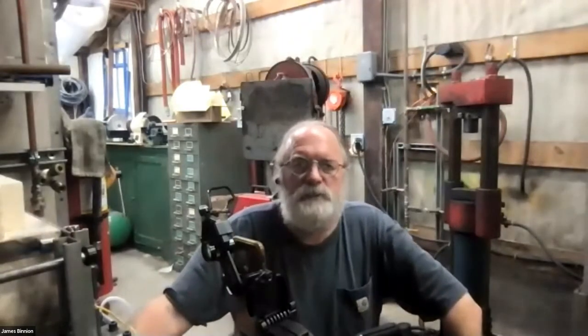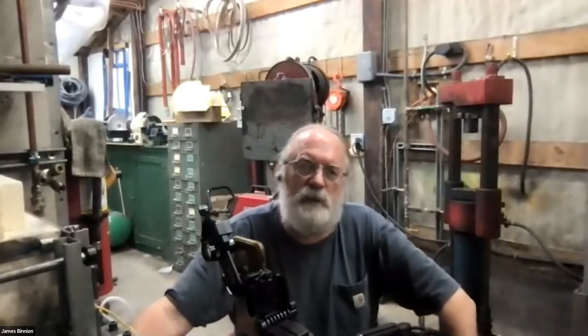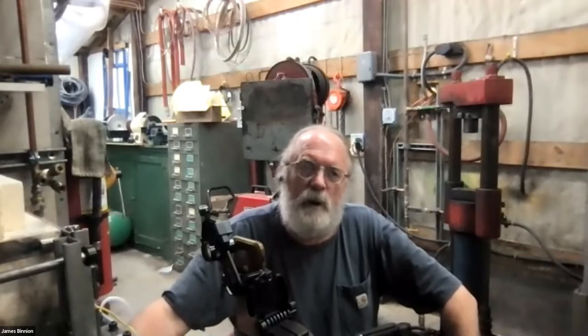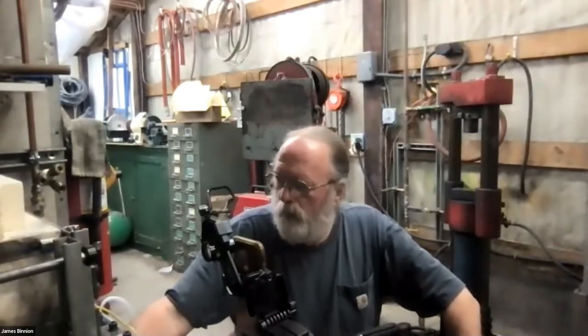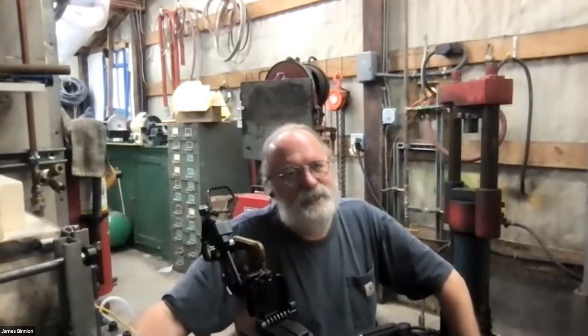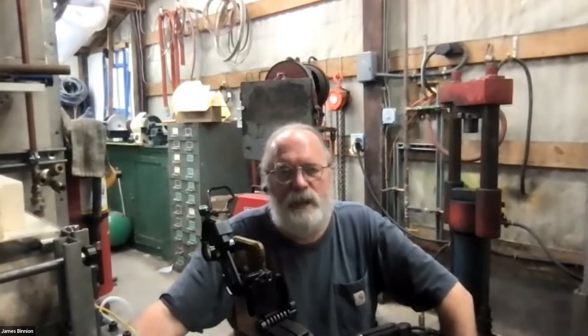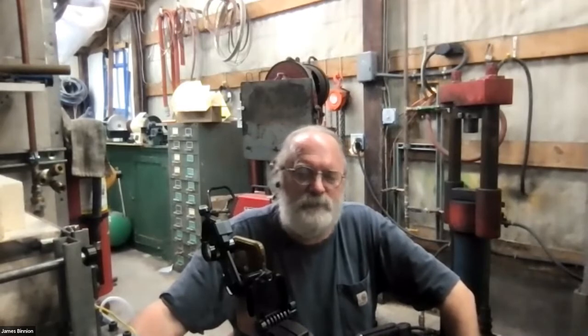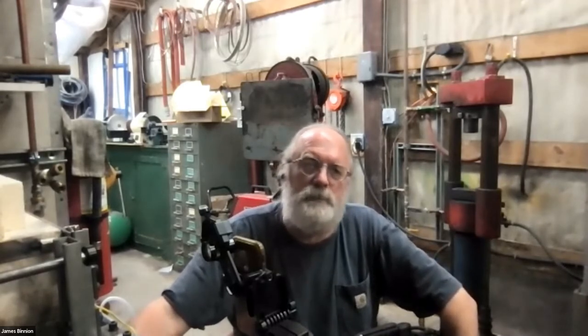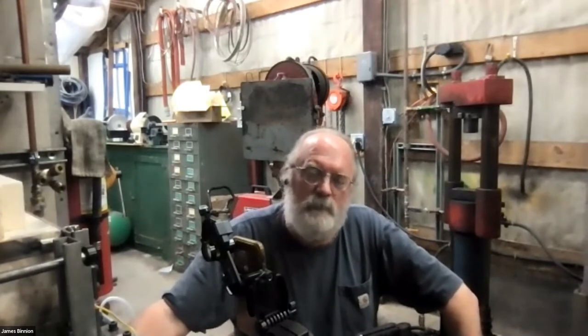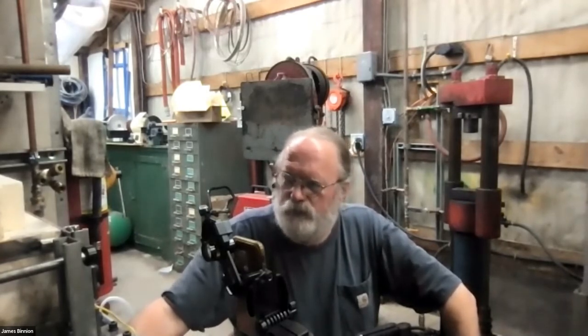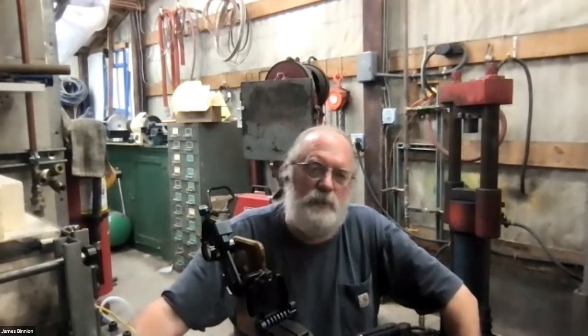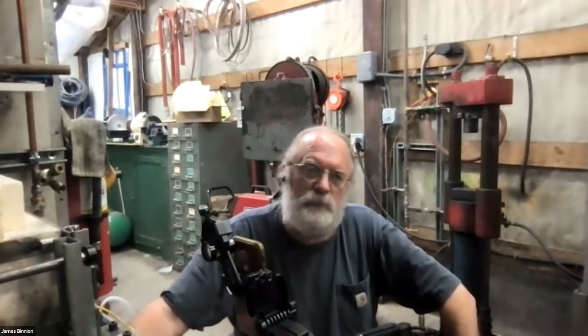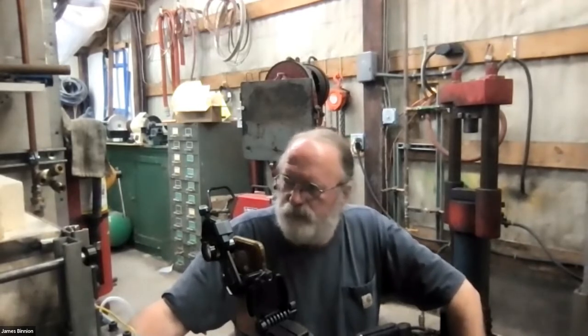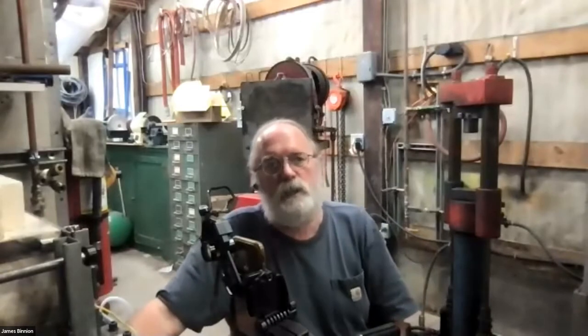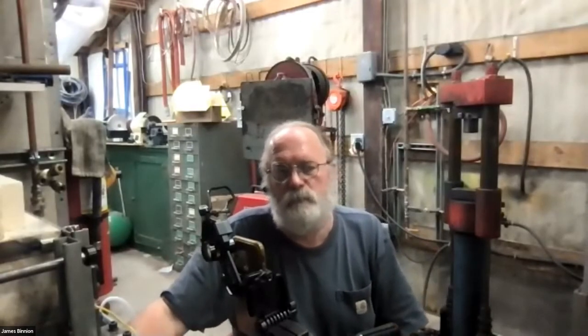Copper and brass is what I normally teach students with. Get a strong color contrast both in the raw and in patinaed form. Brass is a little bit finicky in the laminating, but it's still probably the most straightforward material combination. This bronze I'm using is actually technically a brass. It's called commercial bronze, but it's just a very low zinc brass. And it provides kind of a nice intermediate color contrast against the copper and the brass.